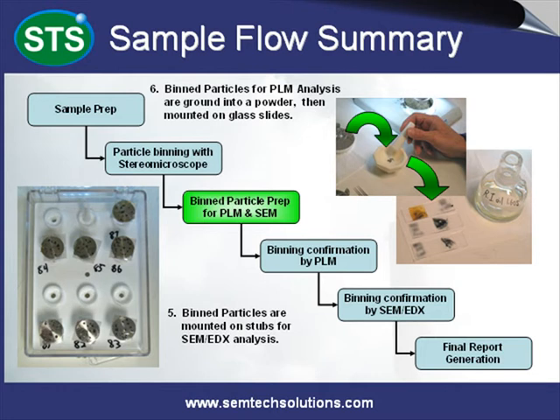For PLM preparation, the suspect particulates are ground into a fine powder. A sub-sample of the powder is placed on a glass microscope slide with a few drops of refractive index oil added. As a note, particulates such as coal tar and asphalt will dissolve in the oil to an orange-brown color, while the other particulate classifications do not dissolve in the aromatic oil.